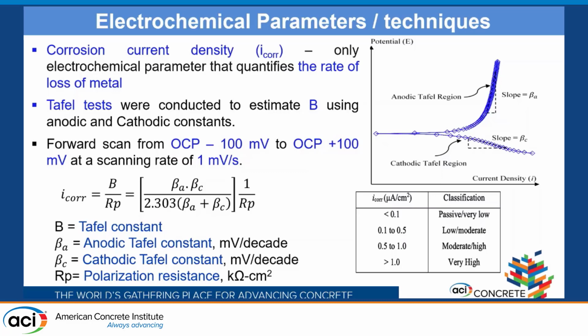So you see two trajectories in this curve. One is the anodic Tafel region, the upper one. You get beta A from there and beta C from here. So you plug in these values and get your I-corr. As per RILEM TC 154, any I-corr above 1 μA per centimeter square would indicate that this system is corroding at a very high rate.